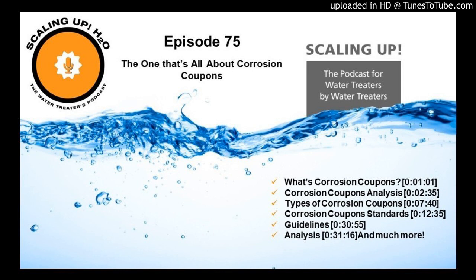We'll get into identifying the different types of corrosion coupons as we move forward, but when the coupon is weighed and everything is said and done, it is measured in a unit called mils per year. Mils per year, quite simply put, is 1,000th of an inch. So if you want to think of that in these terms, a heat exchanger, let's say the metal in the heat exchanger is 1/10 of an inch thick. If you have a corrosion rate of 10 mils per year, it's going to take 10 years to penetrate the walls of that heat exchanger. Now, that's not exactly true, and I can throw a bunch of things in there to say whether that will work or not, but for our definition, that's how we're going to look at that. So it's the removal of the metal that we are trying to protect in the system, and it's the rate at which it is being removed.